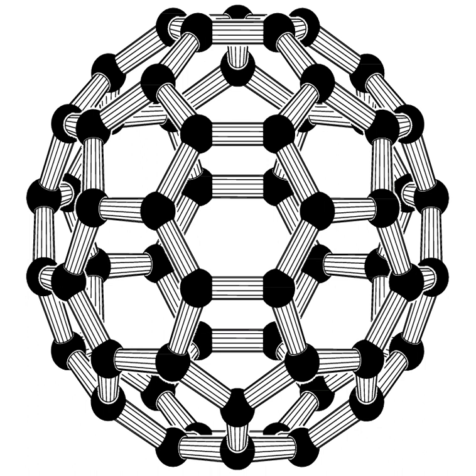Thus, a (5,0) SWCNT that should be semiconducting in fact is metallic according to the calculations. Likewise, zigzag and chiral SWCNTs with small diameters that should be metallic have a finite gap. Armchair nanotubes remain metallic. In theory, metallic nanotubes can carry an electric current density of 4 times 10^9 A per square centimeter, which is more than 1,000 times greater than those of metals such as copper, where for copper interconnects, current densities are limited by electromigration.